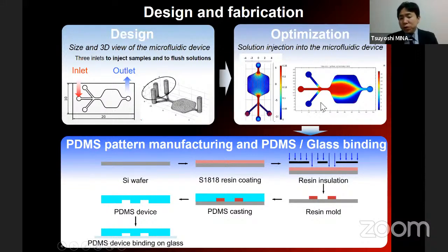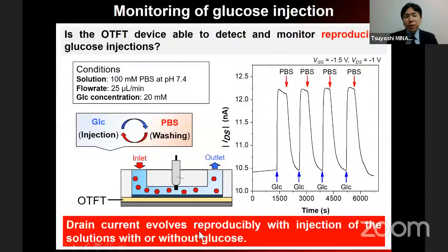So this is a simulation of the solution: how the solution spreads in the chamber. Red is like water. As you can see, the red solution spreads homogeneously in the chamber. That is important to continuously monitor target molecules. After we simulated the device, we fabricated the microfluidic chamber based on the PDMS pattern manufacturing system, as you can see.